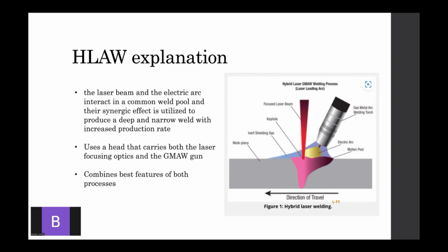It has a reduction in volume fraction of brittle phases, cracks, and thermal distortion when compared to single arc welding or laser welds. In addition, using laser arc hybrid welding allows one to bridge excessive gaps between the workpieces to be welded, which is not allowed during conventional laser welding. Finally, the dual use of laser and arc as the heat source allows one to achieve significantly higher welding speeds, while the penetration depth also increases, translating to overall higher productivity.